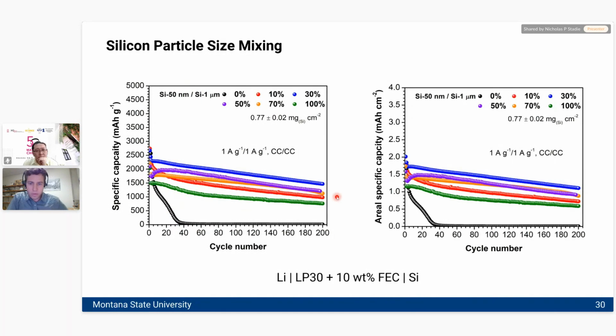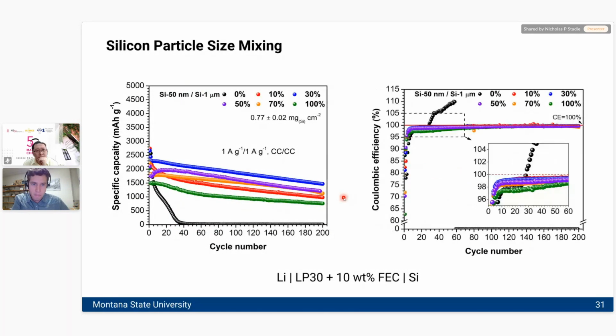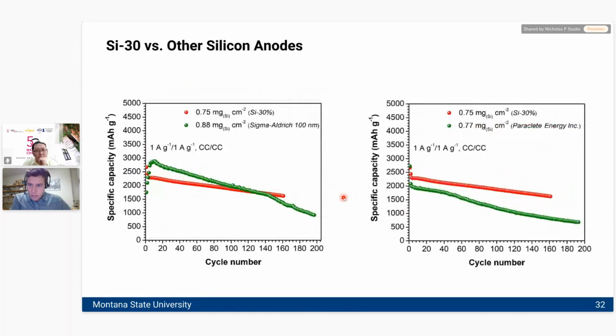So this was a remarkable discovery, and we decided to go forward with this full throttle because this was a really interesting way to improve our silicon anode performance. The material that has the 30% composition of nano in the presence of 70% micron is shown in red here on the right and the left.